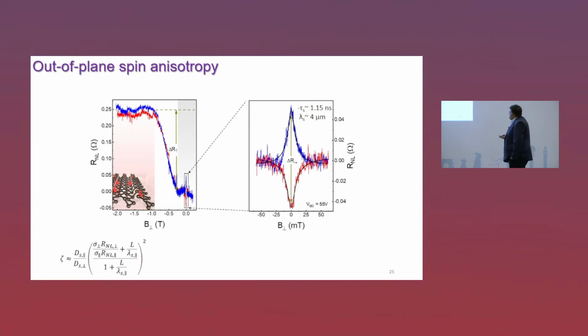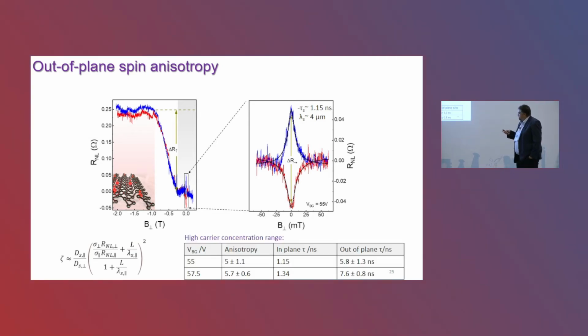plane. We have done some simple calculations, and surprisingly, the spin relaxation times for the spins pointing in the out of plane direction are nearly 5 times better than in plane. For example, in this device, we were measuring around 1 nanosecond spin lifetimes for spins pointing in the plane, and if you force these spins to be out of plane, it was exceeding 6 nanoseconds.